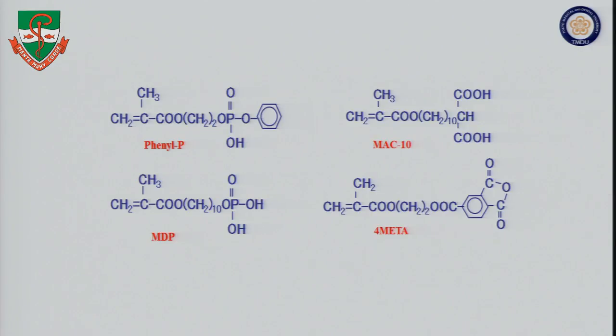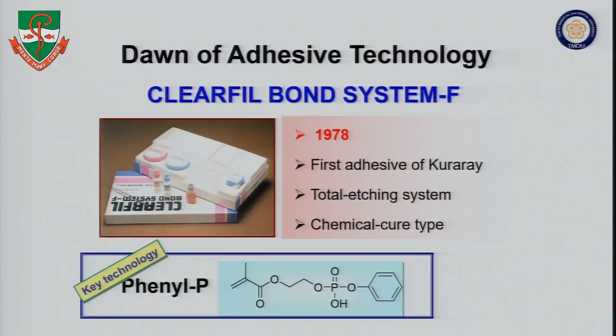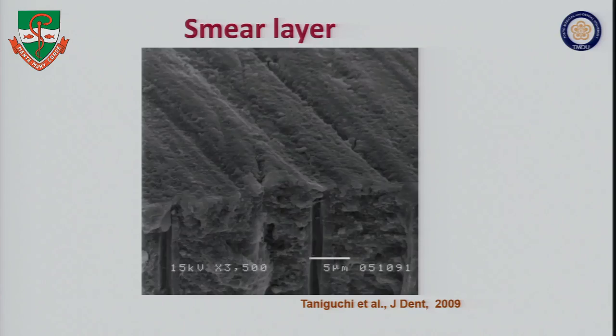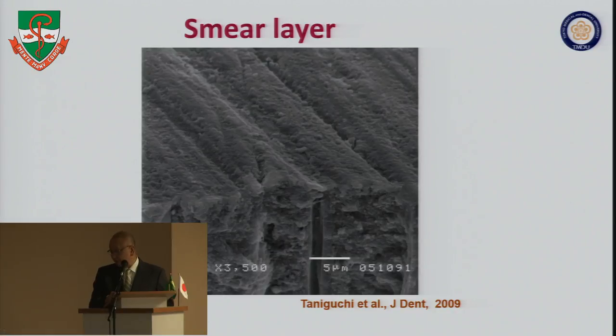For the adhesive materials, the so-called adhesive resin monomers are very important. There are so many kinds of adhesive resin monomers developed by the manufacturers and the researchers in the world. In this material, the first adhesive resin system, Clearfil Bond System F, the so-called Phenyl-P was utilized. And total etching of dentin was necessary because we could not obtain a good bonding onto the smear layer. The smear layer should be removed by the acidic treatment.